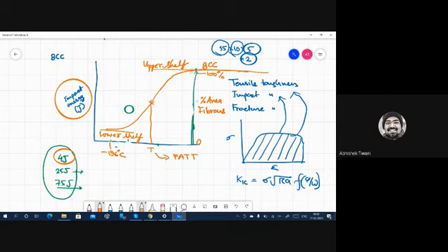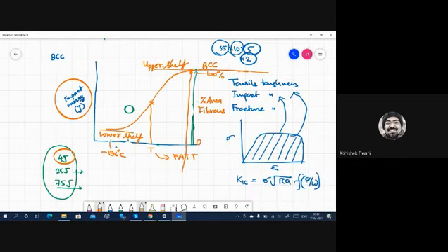So there can be a temperature where the complete area is 100% fibrous. That temperature you can define as FTP, fracture transition plastic temperature. Okay. So these are 2 temperatures which can be defined using the area, how the area of the specimen looks like. Based on energy, you can have different criteria of defining temperatures. And then there is a third criteria also.